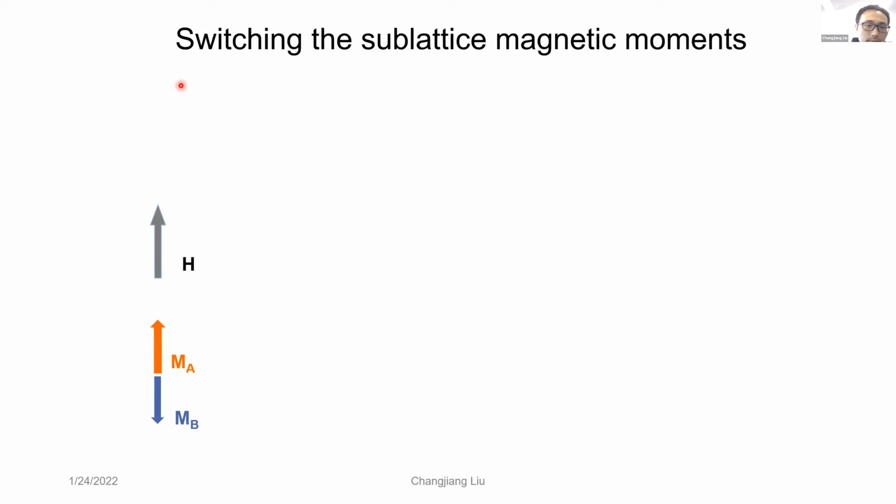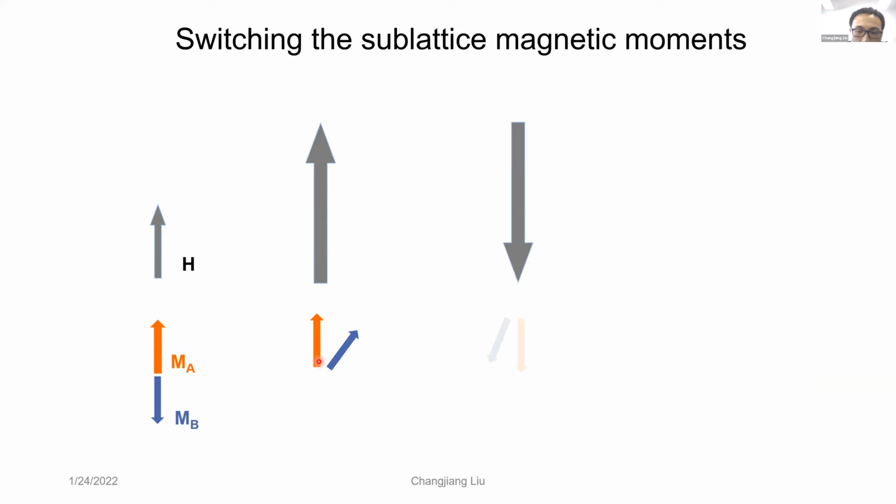Then we need to verify whether this is true, because we can actually manipulate the spin orientation such that initially the two sublattices MA and MB can be configured to the opposite direction. For this measurement, we apply a larger magnetic field, higher than the spin flop condition field. And then we rotate the magnetic field by 180 degrees, and further, we reduce the field. After this operation, the magnetic sublattice orientations of these two can be manipulated such that they are pointing opposite to the original configuration.